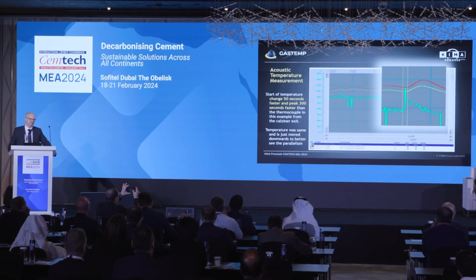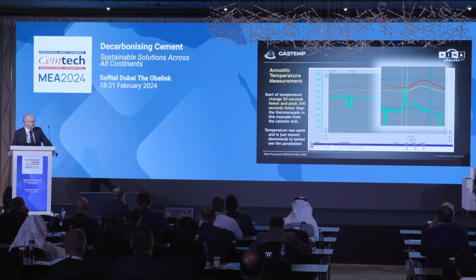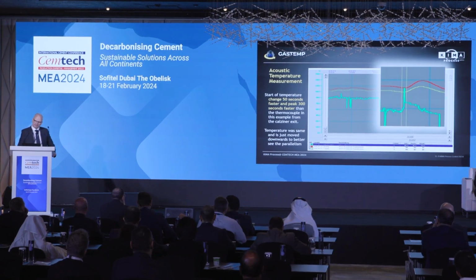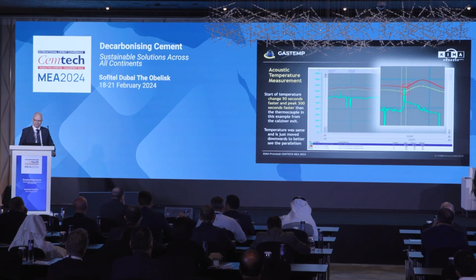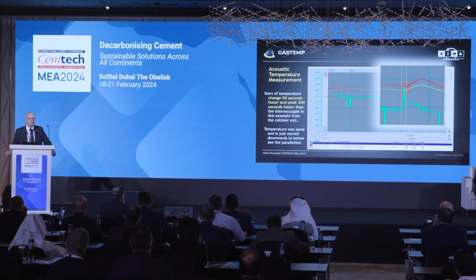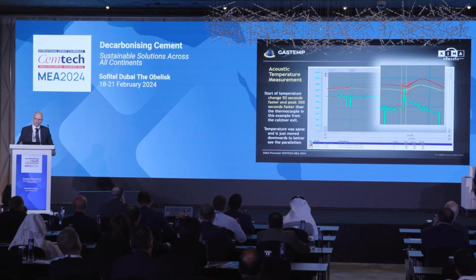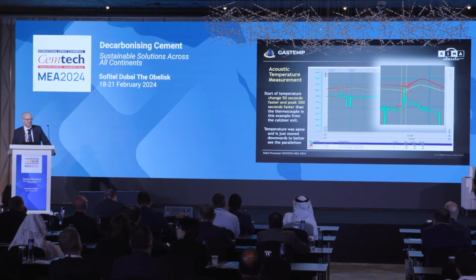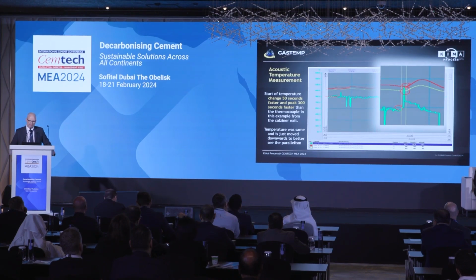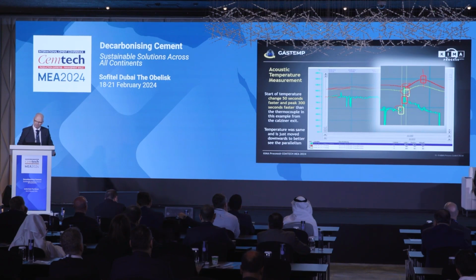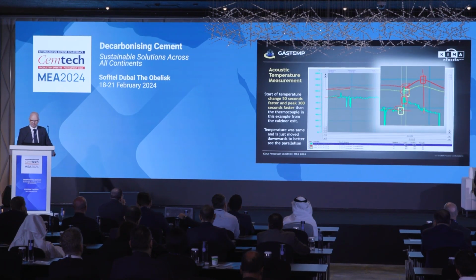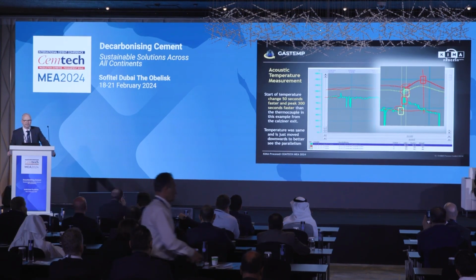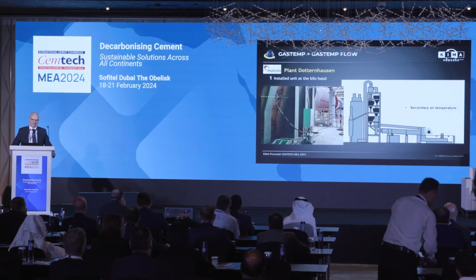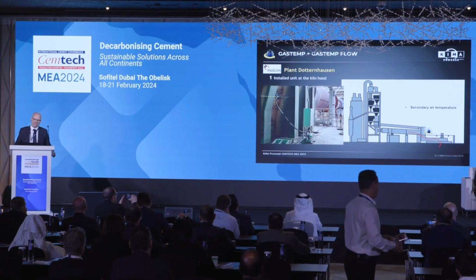You see here a calciner exit. The calciner exit temperature is of course necessary to measure so that you have a good burnout. Today's control happens with these thermocouples, and you see already the offset of the thermocouple is more than 100 degrees, due to infrared radiation from the flame. Now, the acoustic pyrometer sees this temperature increase 50 seconds earlier. 50 seconds is a hell of a time in combustion, you will agree. But more interesting is, today you control on these thermocouples, and when the thermocouples show there is a peak, the acoustic pyrometer says, this is already history. Interesting for process optimization is also the secondary air temperature, the heat recuperation from the clinker cooler into the kiln.